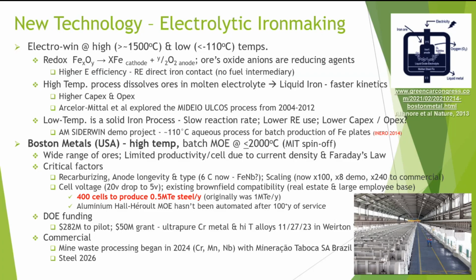The low temperature solid iron process is, of course, lower energy use, and lower capex and opex, but it's a slower reaction rate. And ArcelorMittal does have their Siderwin demonstration project running, which is a 110-degree aqueous process in batch to produce iron plates. The American equivalent is Boston Metal, which is high temperature. It can process a wide range of ores, but it's limited in productivity per cell because of the current density in Faraday's law. The critical factors for them are ability to recarburize once they've got the iron, longevity of the anode and choice of the anode, and scaling.